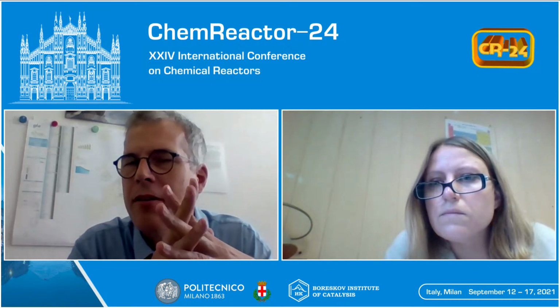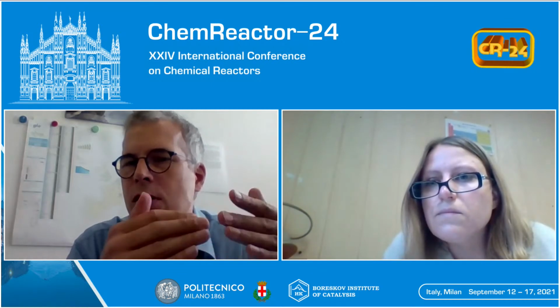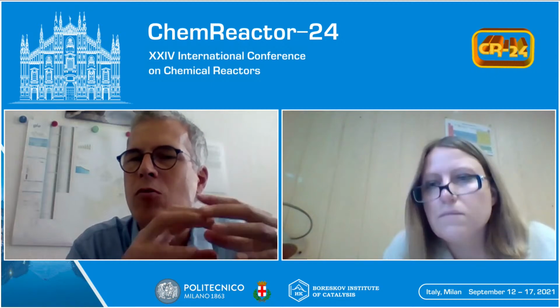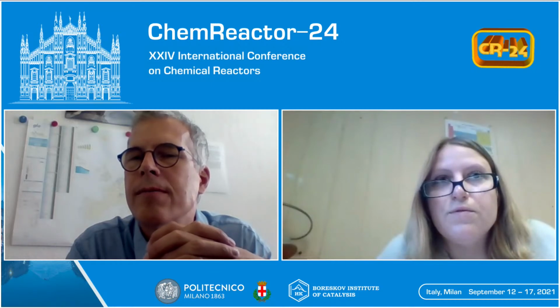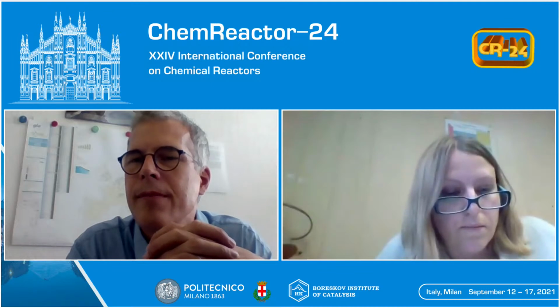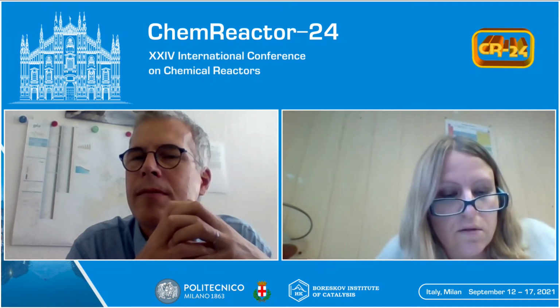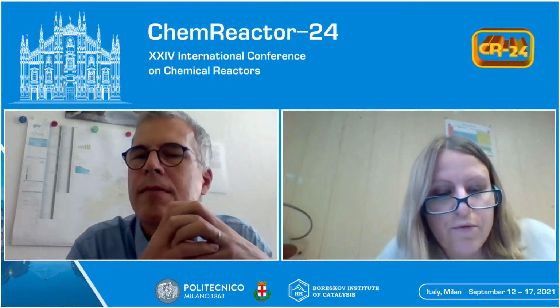I'm definitely not a specialist in your field, so the question I had: if you do the dry reforming of methane and CO2 inside the membrane, at the end your main products, CO and hydrogen, go out on the other side, right? Would that be rather an extractor type of behavior, where we use the selective separation of the reaction products to shift the equilibrium? Yes, yes. The membrane reactor in extractor mode possesses selective separation, and it can influence the equilibrium of the chemical reaction.